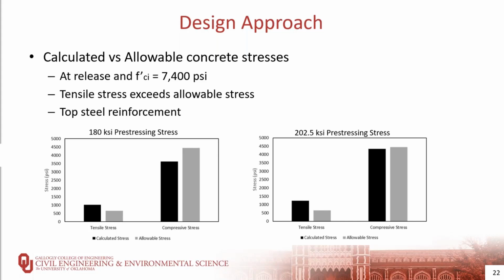In both pre-stressing stress cases, the compressive stress did not exceed the allowable. However, when we talk about the tensile stress, it did exceed the allowable stress. So top steel reinforcement was added to accommodate that high tensile stress in the hybrid and the conventional concrete beams that we did.